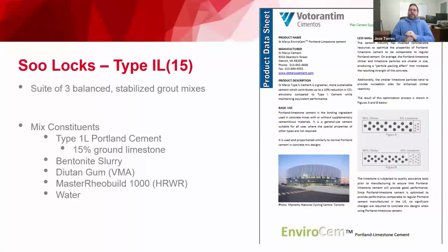Soo Locks, we did this job the first time we used type 1L at 15%. So when you see type 1L, that number in parentheses will tell you how much limestone content is in your mix. That job had 3 balanced stabilized grout mixes, using 1L Portland cement with a 15% ground limestone mix. Generally, the mix components were the same as the other two.